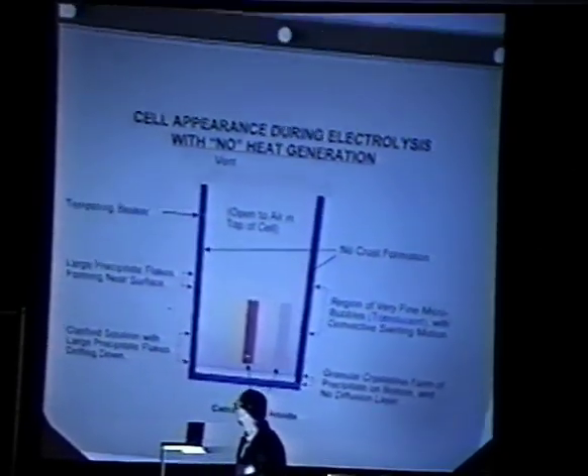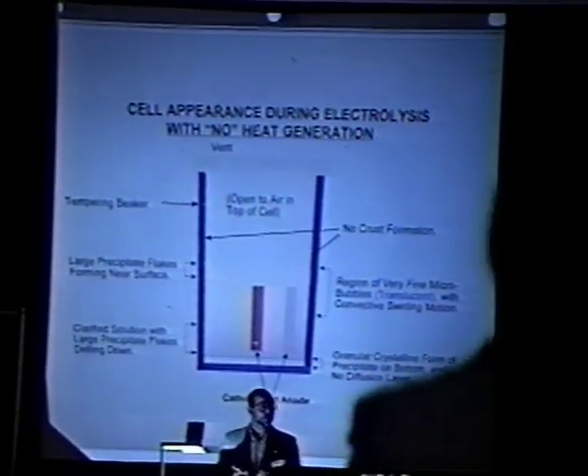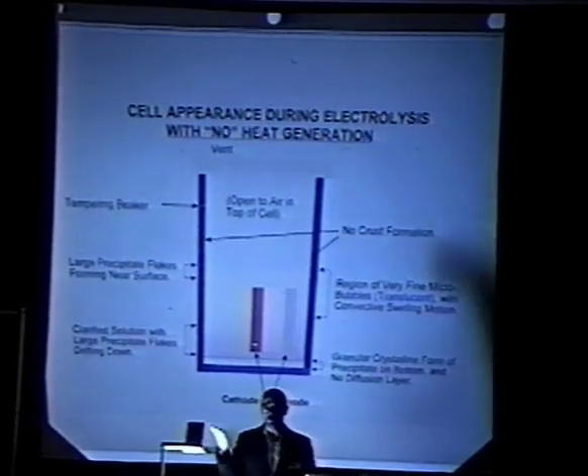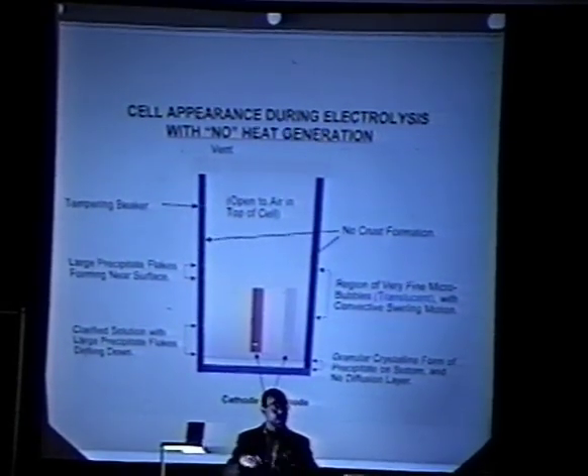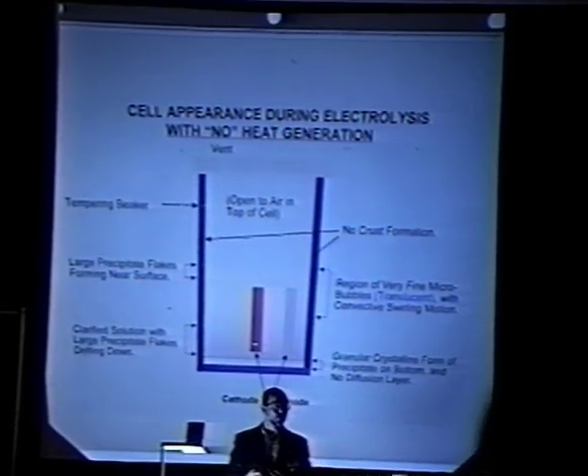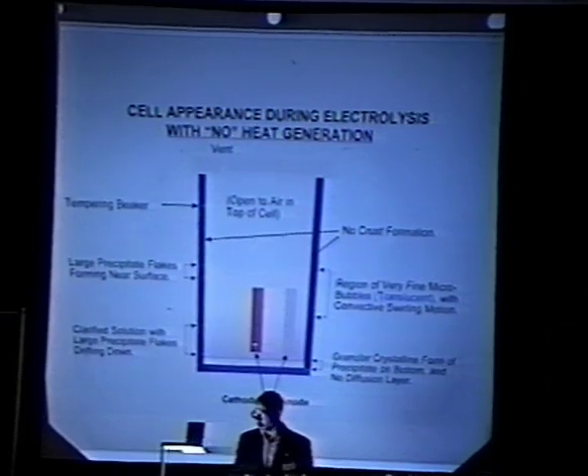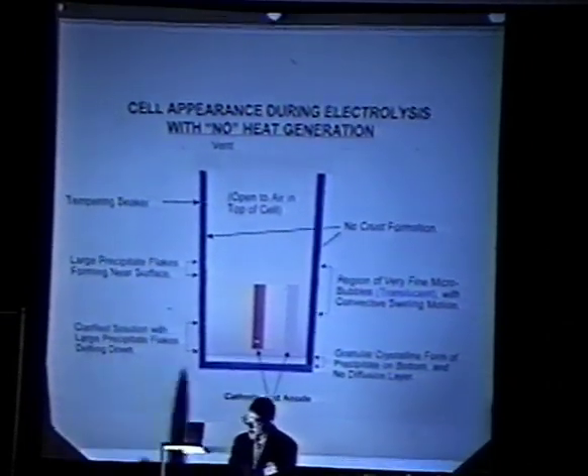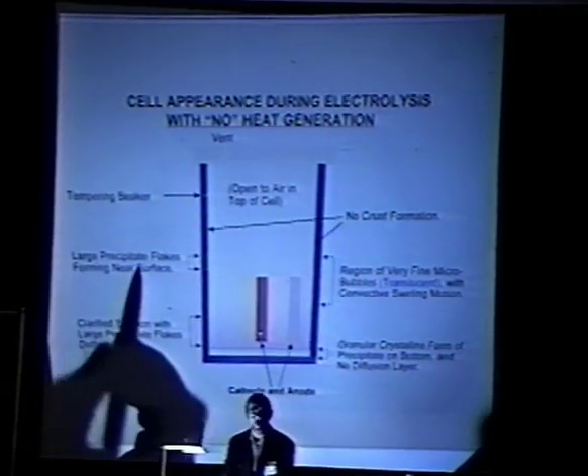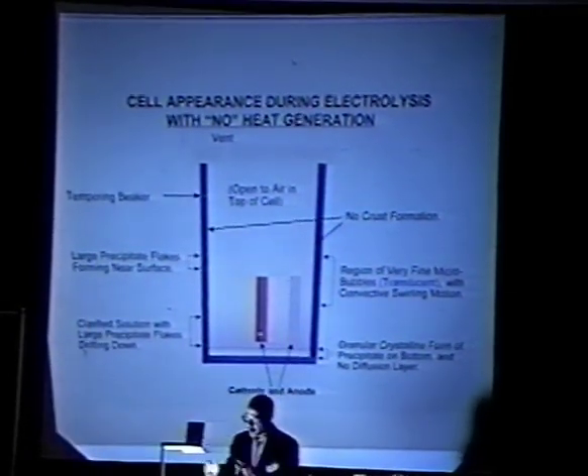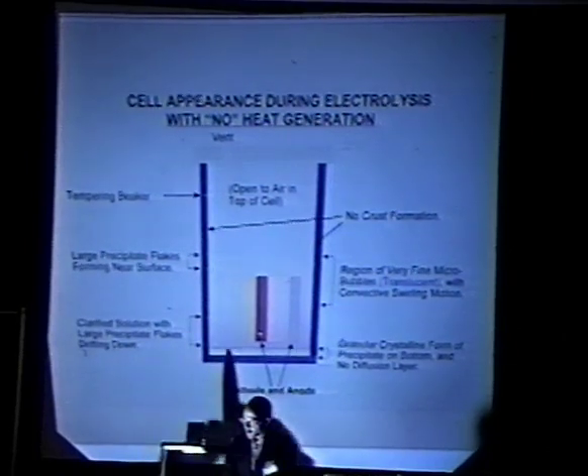Now to compare that with no heat generation, with just electrolysis, I can take this same cell and run a lot of current through it, and in fact percolate some CO2 gas on top or whatever, and get a lot of this carbonate to form as well. There are ways to force the carbonate formation, but in this case, these flakes form all very near the surface, and they tend to be very large. None of them are small, they're all quite large, and they just fall down through the clarified solution and form at the bottom.